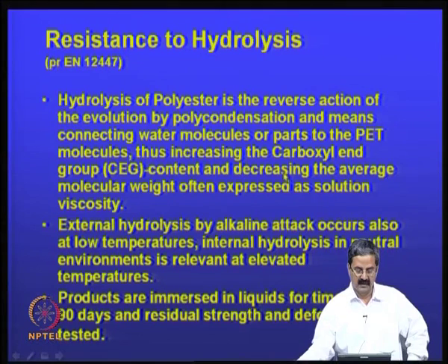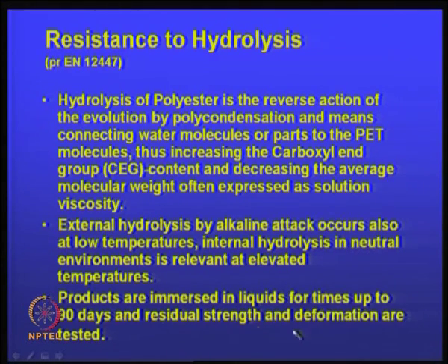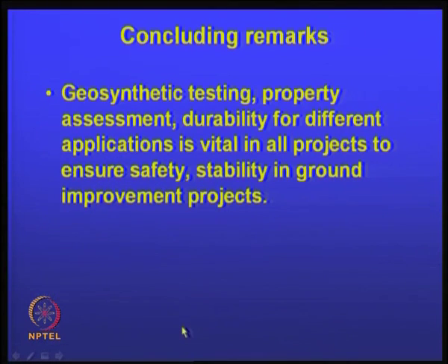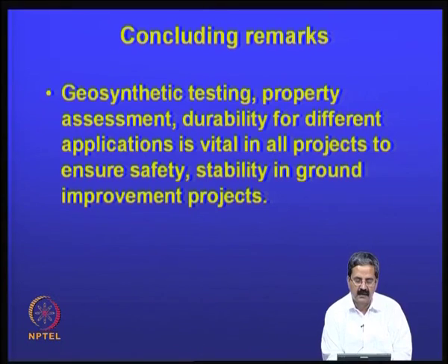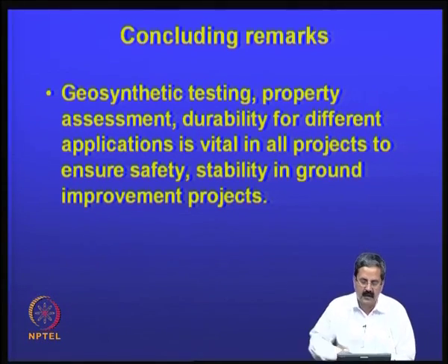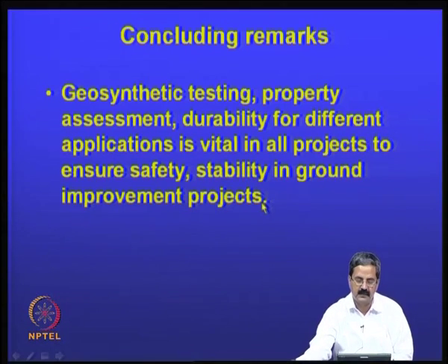Why those things happen is that, due to this hydrolysis, the average molecular weight will come down. So there are a couple of tests that are done. What we do is that the products are immersed in liquids for times up to 90 days and residual strength and deformation are tested. So you have a number of testing procedures which are well established.